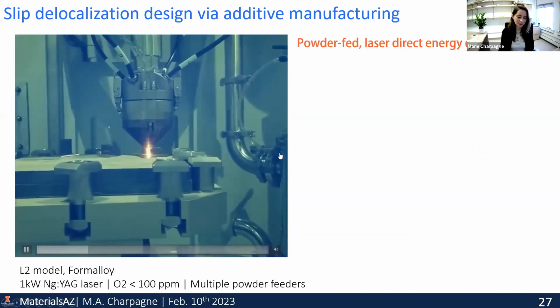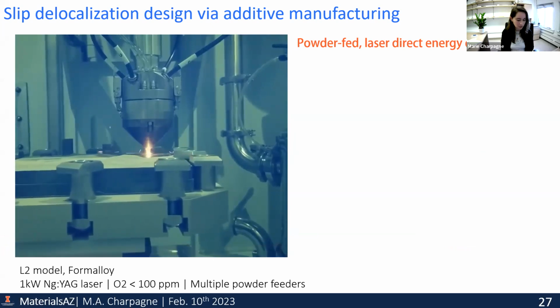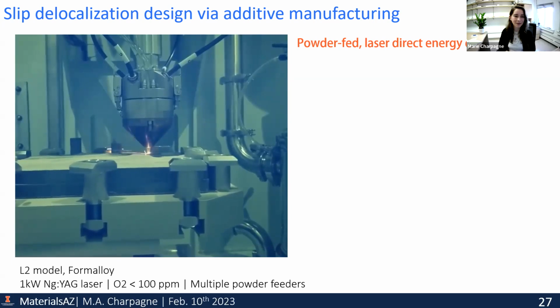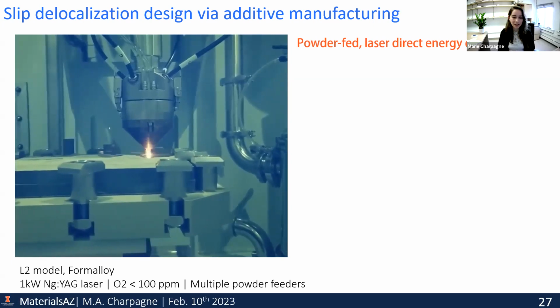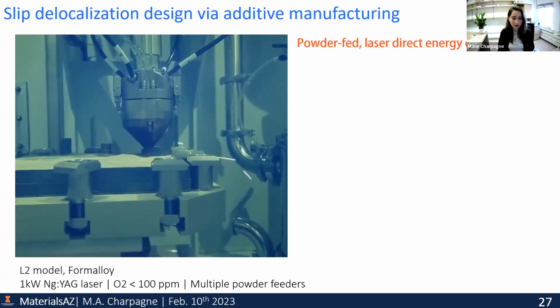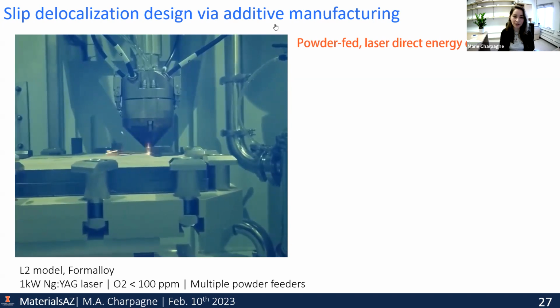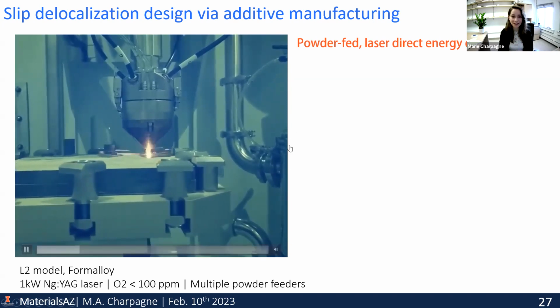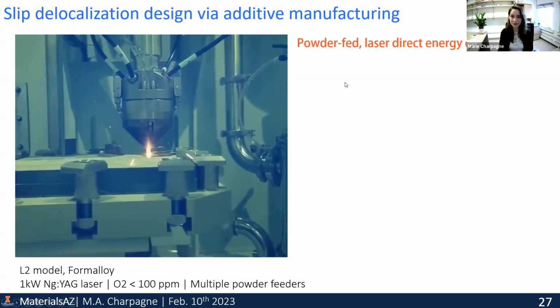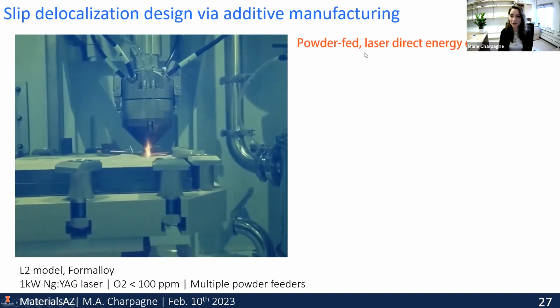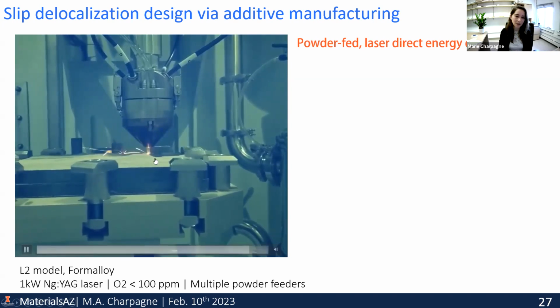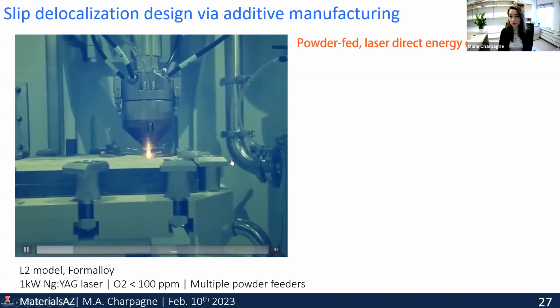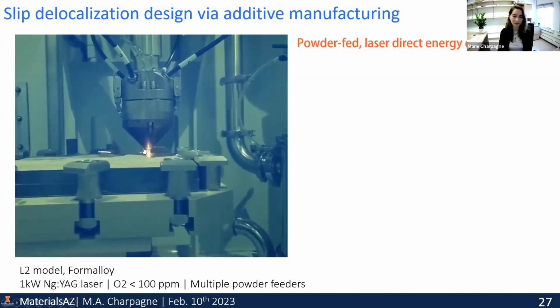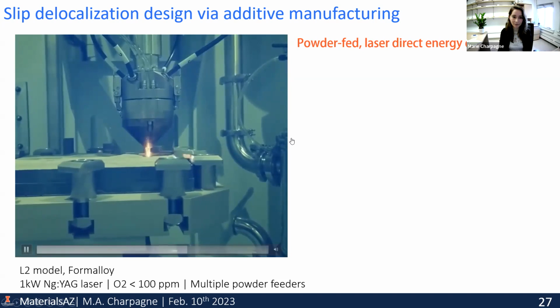All right, but this was on a material that we put zero effort in actually optimizing whatsoever for our slip delocalization approach. And now what we're working on in my lab is actually printing our own alloys. And there is no better way of having your own printer to do that, because we need to spend a lot of time doing this. So we're now printing our own alloys and using this technology of laser direct energy deposition, where we blow powder underneath a laser source, and we build our materials in a laser cladding process, essentially.